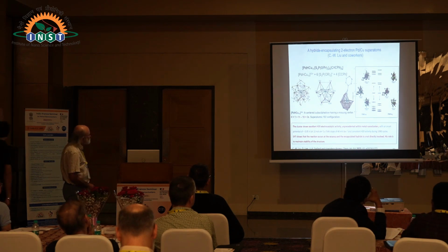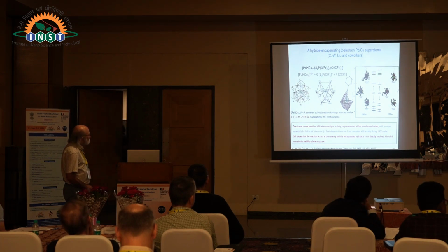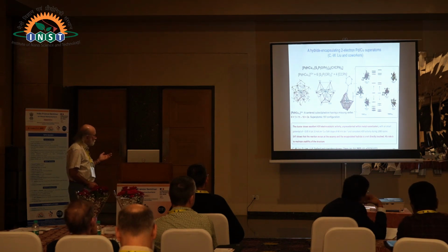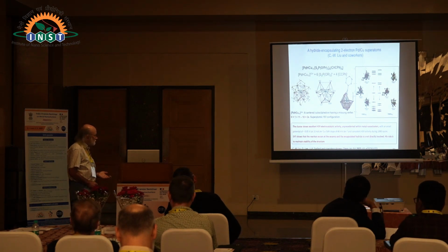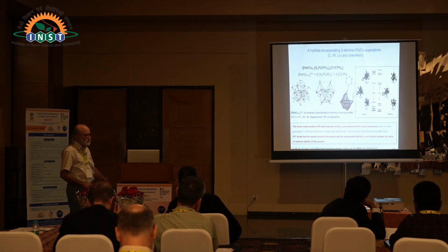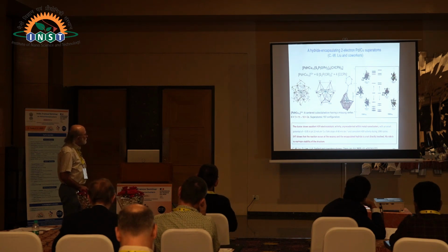What is interesting with this compound is that it's a very good electrocatalyst in the hydrogen evolution reaction. Very good, actually. So we could think that the hydride is involved in the catalytic cycle, but it actually is not. From DFT, it's clear that it is there only to provide stability to the system. It is not exchanged.